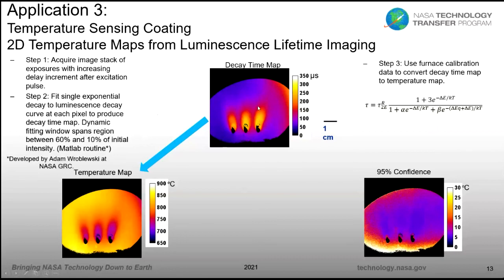That's what you see over here. If you look under one of the air jets, the decay time is substantially longer than in the uncooled region. The decay times are substantially shorter where it's uncooled. I've shown you a couple of graphs already that show the decay is faster as you increase the temperature. Well, I find decay times interesting, but the end user maybe not so much.